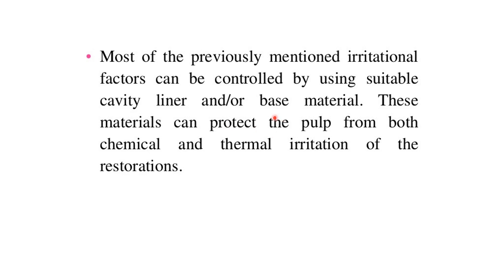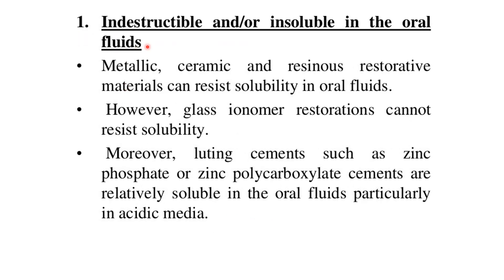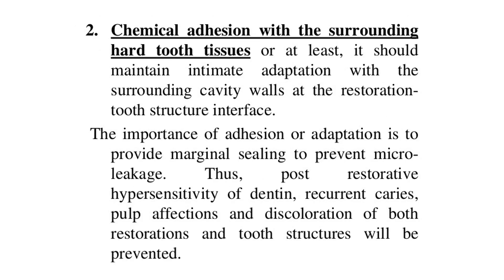Physical properties of restorative materials include: being indestructible and/or insoluble in oral fluids; chemical adhesion with surrounding hard tooth tissues; ability to withstand functional forces without fracture; and maintaining dimensional stability inside the cavity. Metallic, ceramic, and resinous restorative materials can resist solubility in oral fluids. However, glass ionomer restorations cannot resist solubility. Luting cements such as zinc phosphate or zinc polycarboxylate cements are relatively soluble in oral fluids, particularly in acidic media. Chemical adhesion — or at minimum intimate adaptation — with surrounding cavity walls at the restoration-tooth structure interface is important.